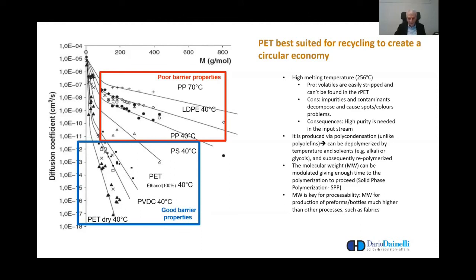This leads to another form of recycling, which is not completely discussed in this presentation, which is chemical recycling, which is equally safe, but less frequent because it is less economically sound. So the PET can be modulated in terms of molecular weight in the polymerization phase, giving enough time for the polymerization to proceed in the so-called solid phase polymerization, and this leads to an increase of the molecular weight, and then to better volatilization of the contaminants and possible decomposition products.